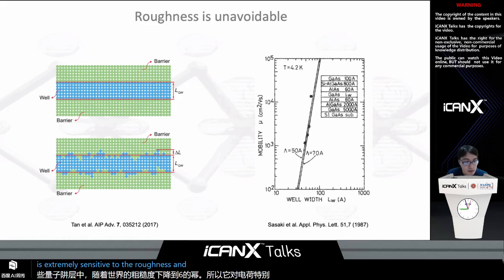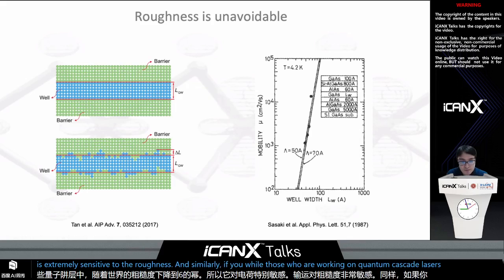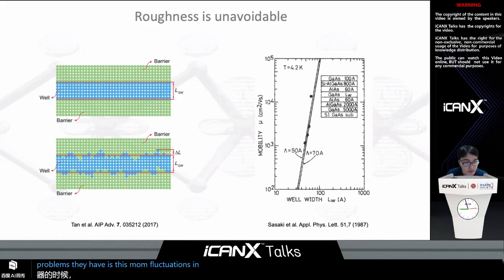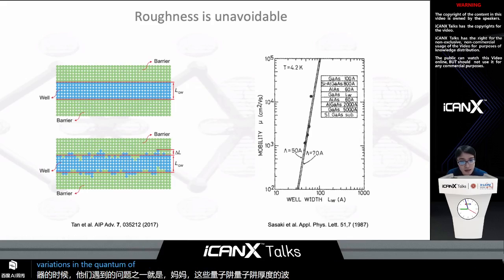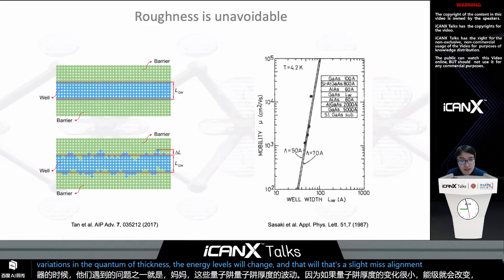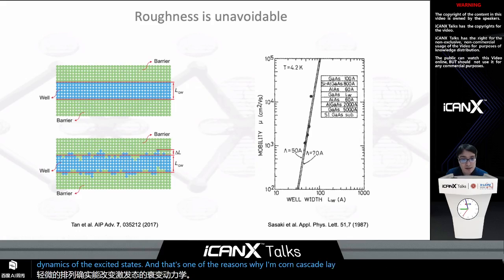And similarly, those who are working on quantum cascade lasers have a problem with these fluctuations in the thickness of the quantum wells, because if you have slight variations in the quantum well thickness, the energy levels will change, and that slight misalignment can really change the decay dynamics of the excited states. That's one of the reasons why quantum cascade lasers have still not been perfectly miniaturized to the extent that other lasers have been miniaturized.